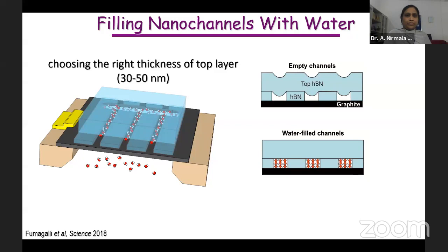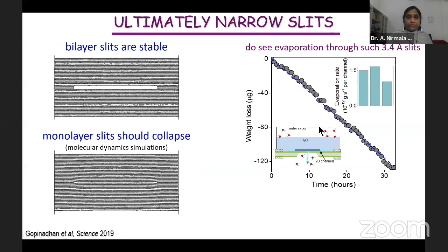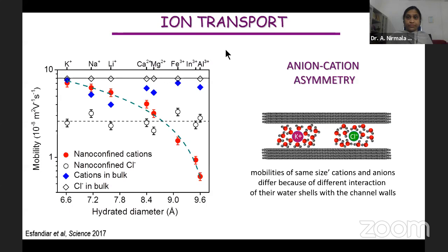Hydration shells, let me see whether this image is somewhere here. On this image, this is our cartoon of what's going on. The orientation of hydration shells is different. This is what we believe, because the interaction of oxygen with graphite is known theoretically to be stronger. This is why we believe chlorine moves slowly, because its hydration shell interacts more, but potassium is a different situation, less interacting, so it moves more easily through the surfaces.